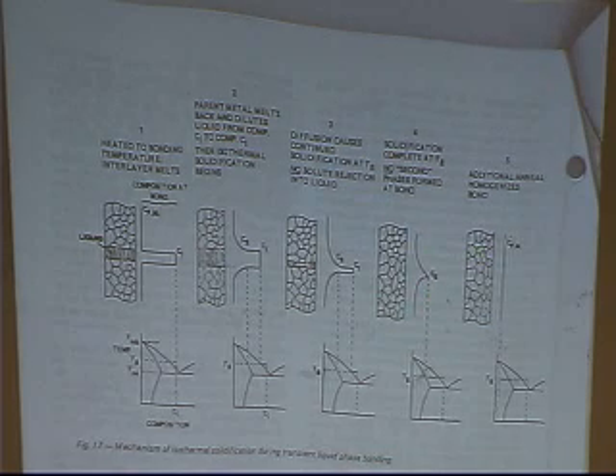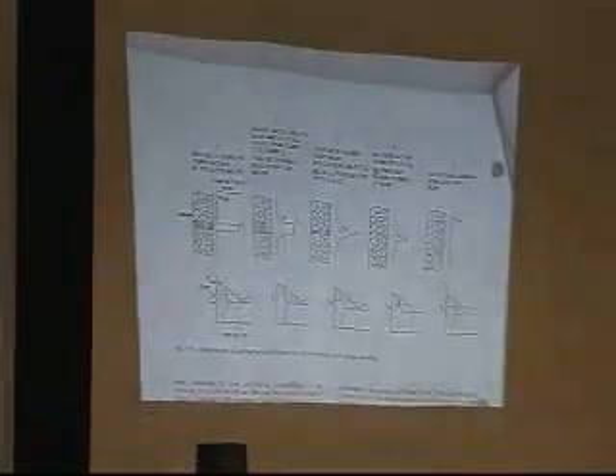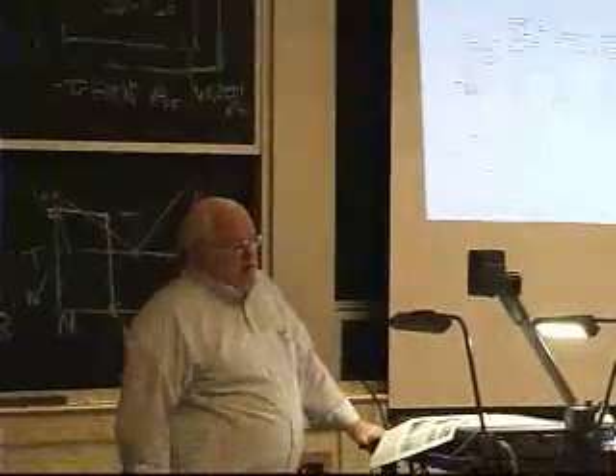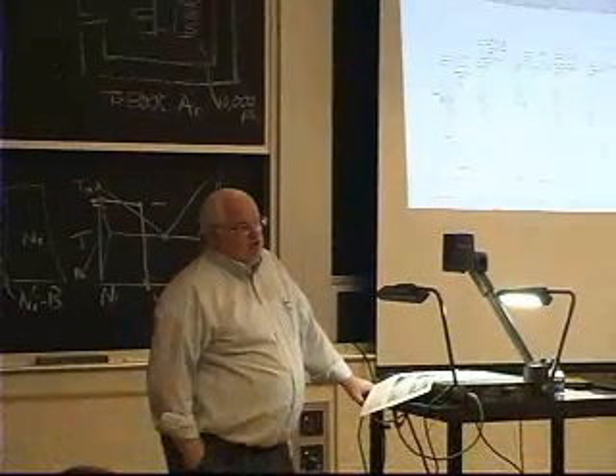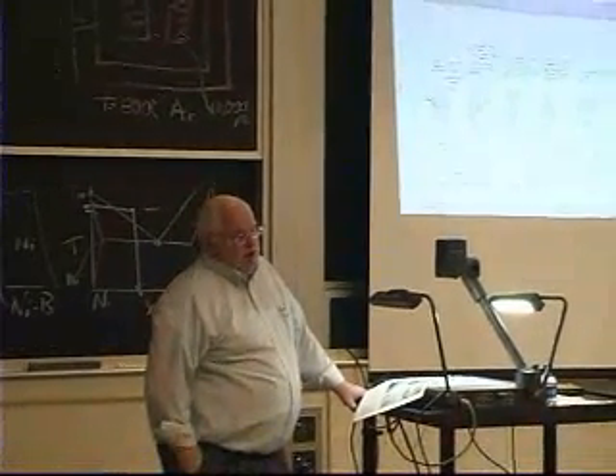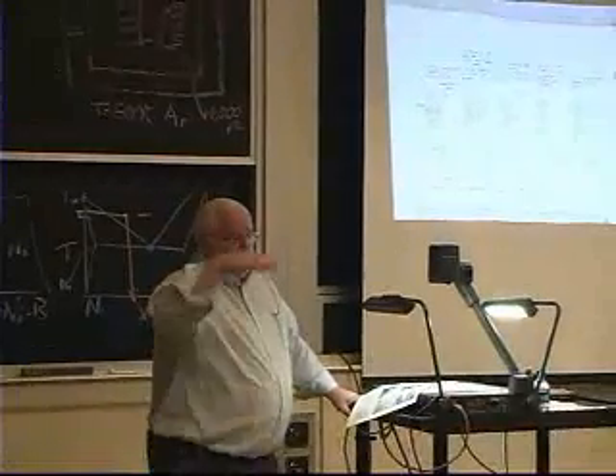Eventually, I will end up with a virtually perfect bond. Almost, there is still a small compositional variation that I can measure, but you can't see it in the microscope. As you're holding it, as you're waiting for the diffusion of boron, are you also increasing the temperature? Nope. You could, but it would slow you down. You don't have to. And we don't usually have to get that fancy. So it's not like a brazed joint anymore. It's like a weld. You're making a weld at low temperature. I would say it starts as a braze and ends as a weld. But you don't have to raise it up to high temperatures.